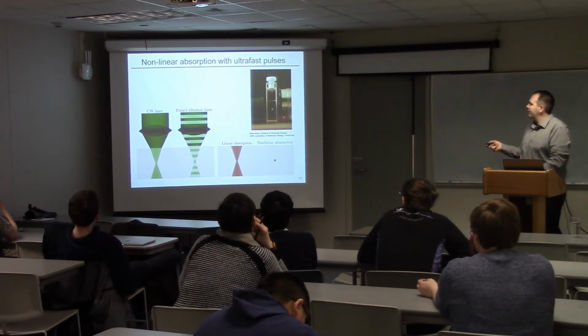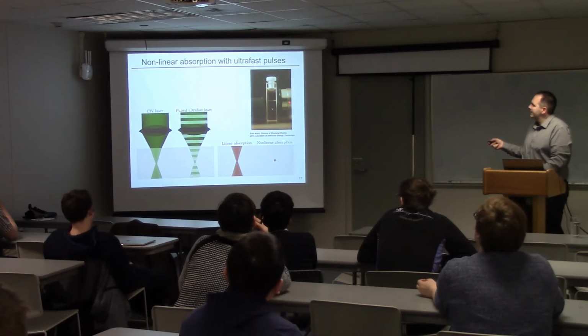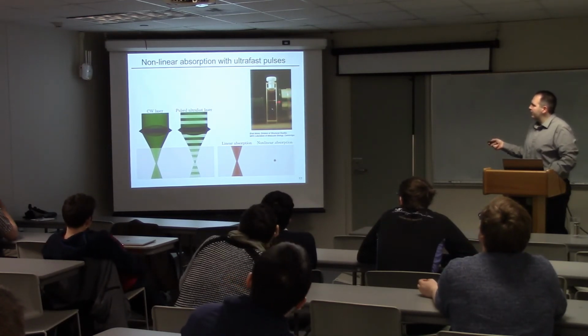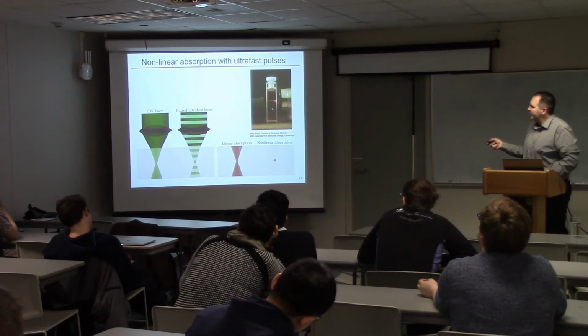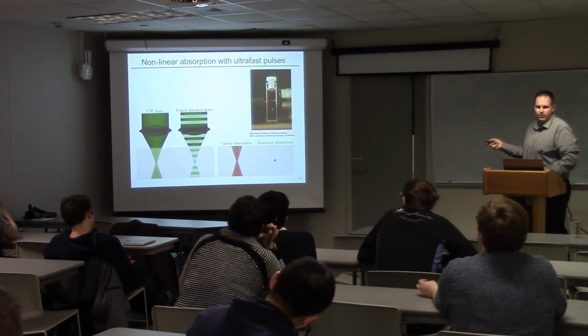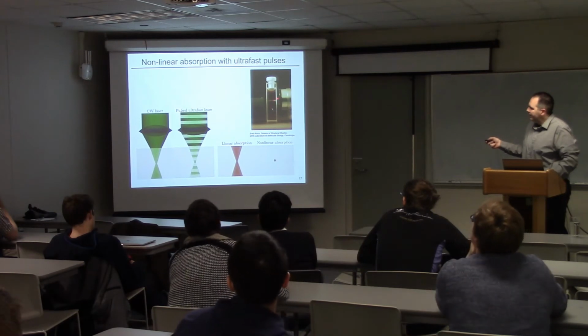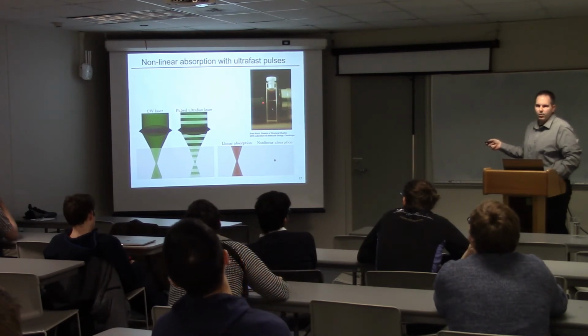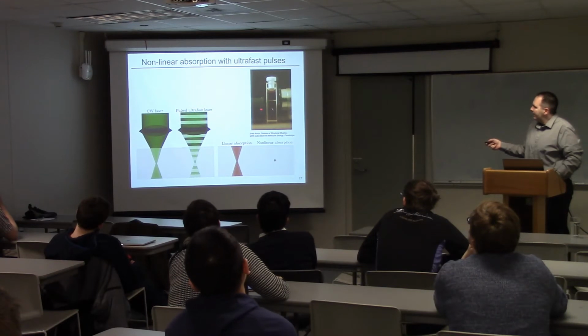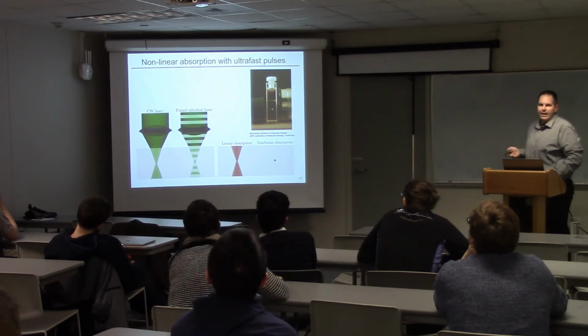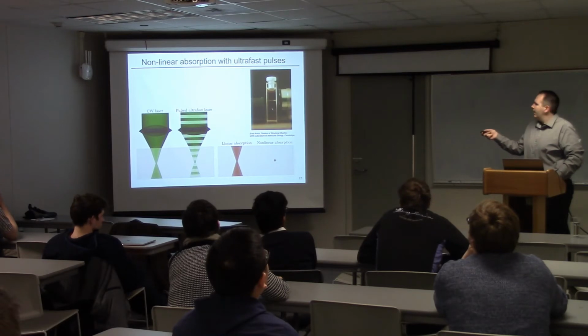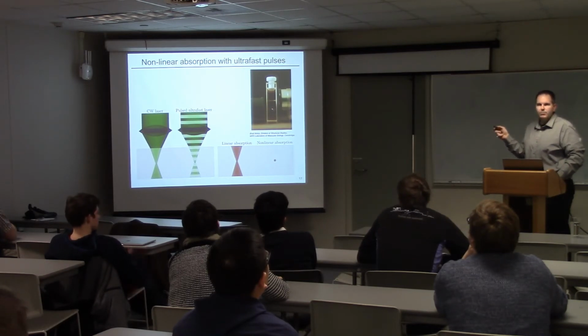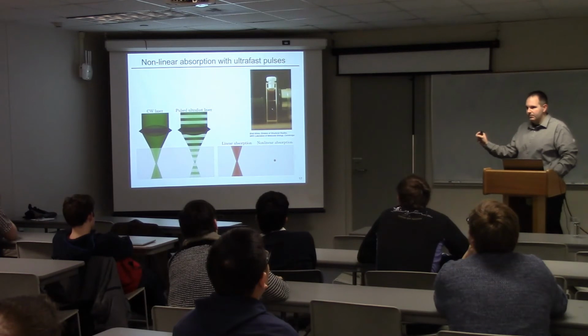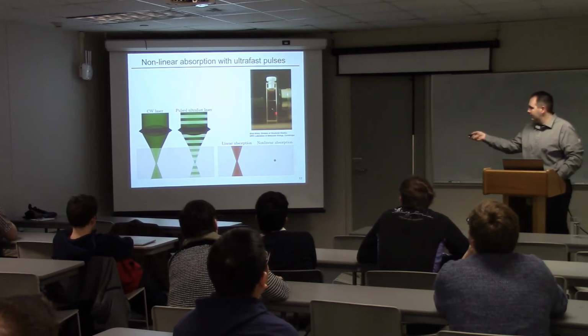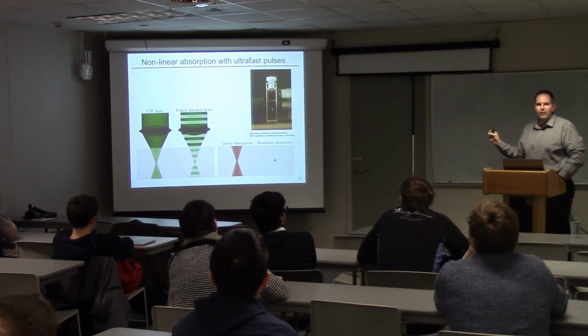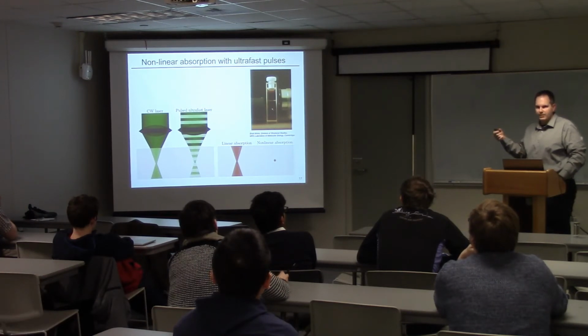If you look at this picture here, there's a laser coming in from the right, and it's showing linear absorption. You can see the laser light focus. It's being absorbed by the material, and there's a fluorescence or a change in color here, and you see the shape of the beam being focused and then defocused after the focal point. On the left, there's a very small spot, and that is where the nonlinear action is taking place. You have absorption only in the small focus point of the lens, and that's the only spot where you have sufficient intensities to create this absorption.